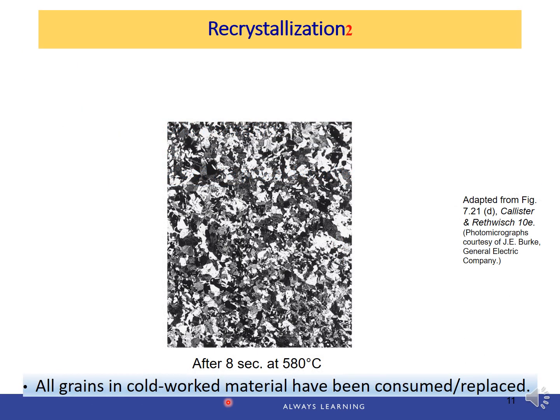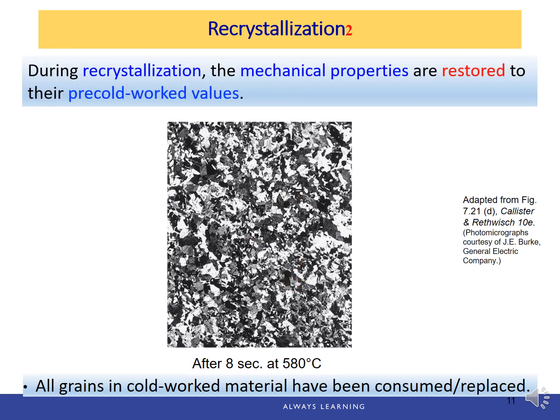And after 8 seconds at this temperature, 580 degrees Celsius, all grains in the cold worked material have been consumed or replaced by finer grains. So during recrystallization, the mechanical properties are restored to their pre-cold worked values, which means the material becomes more ductile and softer but weaker.